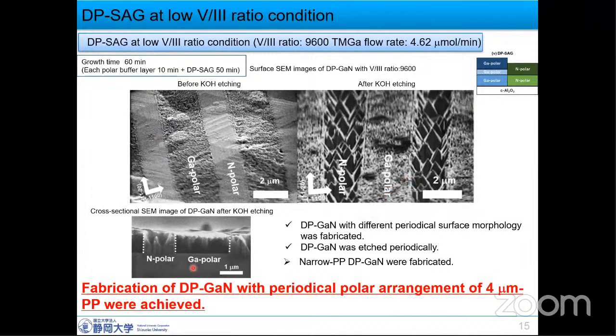Following the cross-sectional SEM image, DP GaN with an abrupt interface between each polar region. Following this slide, we achieved fabrication of DP GaN with periodic polar arrangement of 4 micrometer pitch pattern.